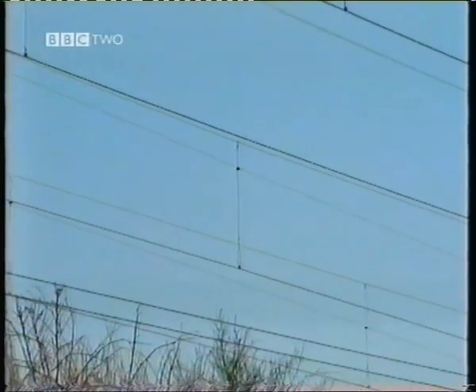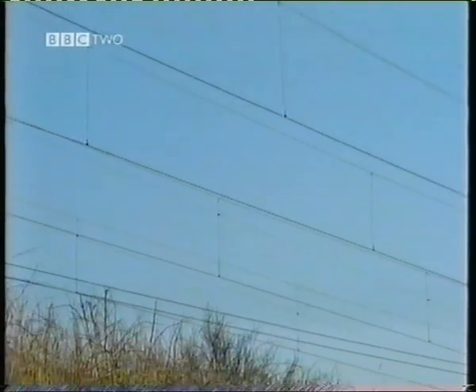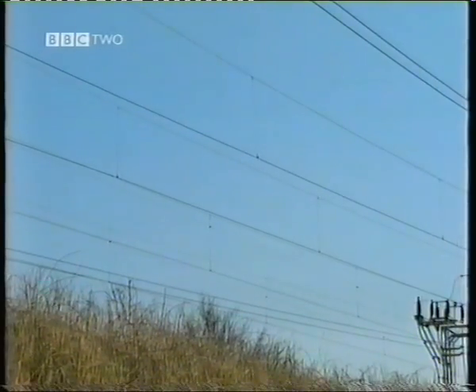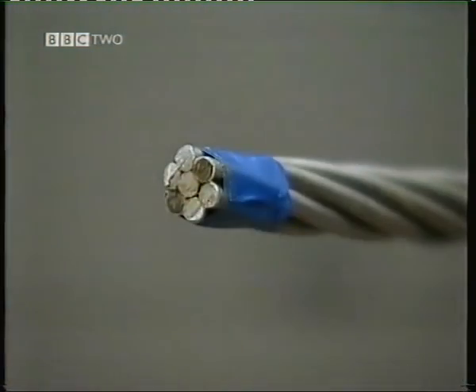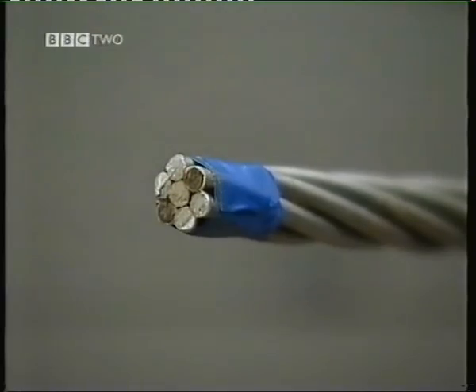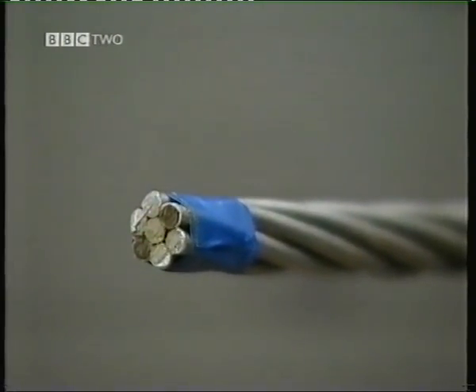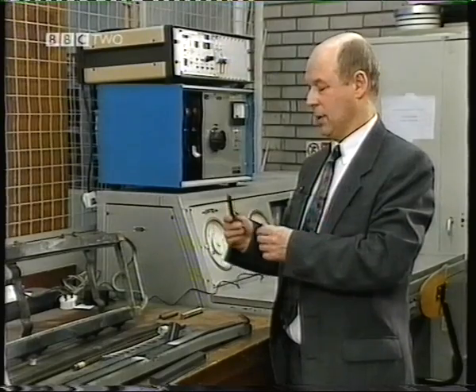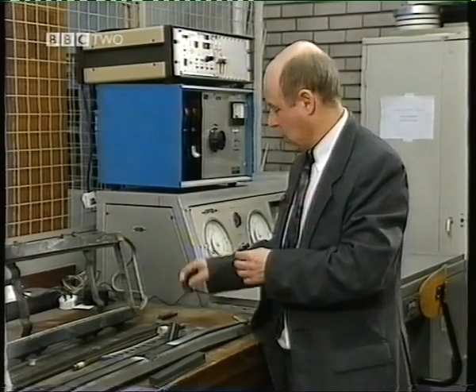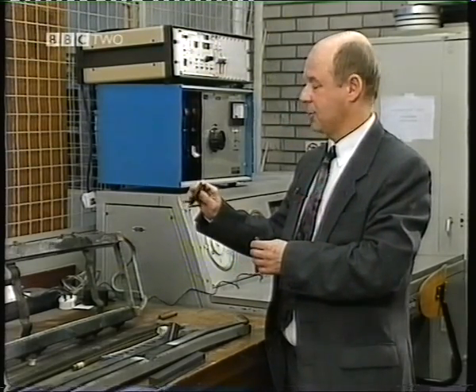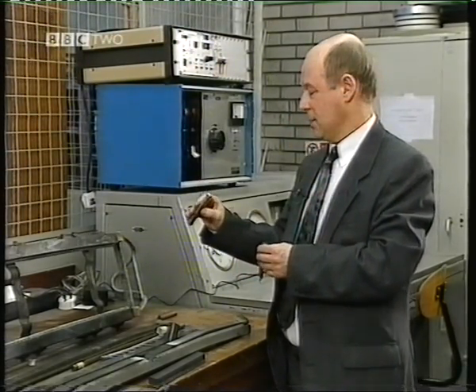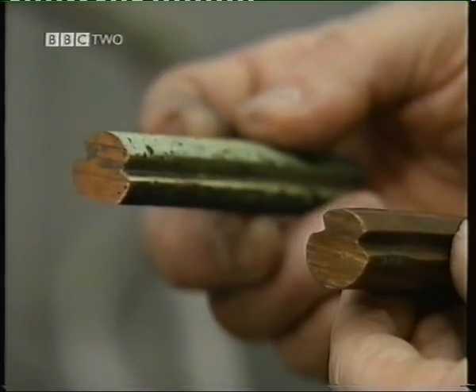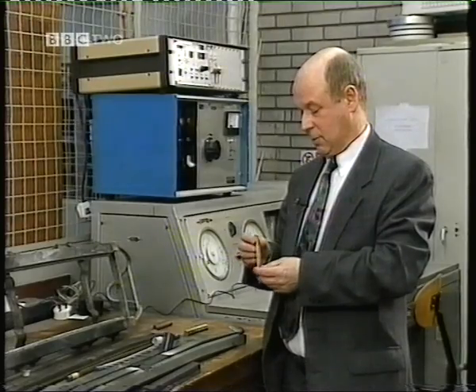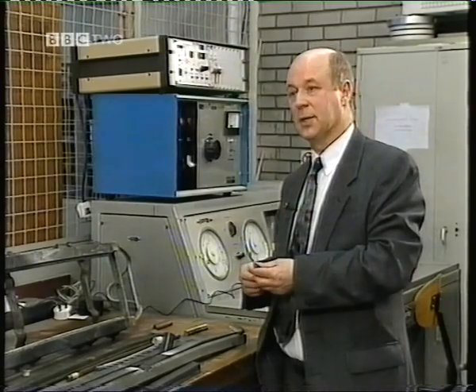Until the 1970s, we used an all-copper system, but with the rising price of copper, we investigated an aluminium catenary wire, an aluminium with 2 steel strands inside for reinforcement. With 1 ton of tension in the cable, what do you do about creep? On new wire there isn't much of a problem, but as the wire wears and becomes half worn, the creep becomes significant, and the copper contact wire is actually alloyed with cadmium to reduce the creep. Other alloys such as silver, which we might investigate in the future.